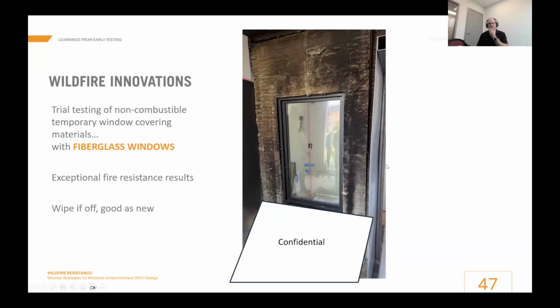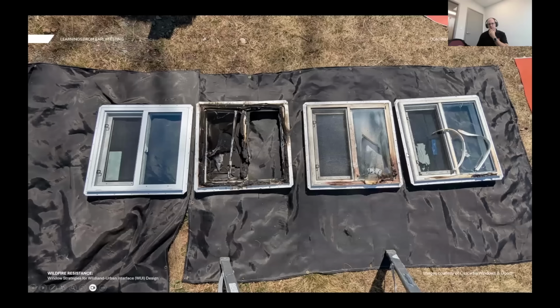We also tested it with vinyl. These two samples on the right are what happened to the vinyl windows with the window coverings. They melted, the glass broke, the windows are destroyed, but they passed the test in the sense that the building wasn't lost. They kept the fire out of the building. So that early research is going to be, I hope, valuable for existing building owners.